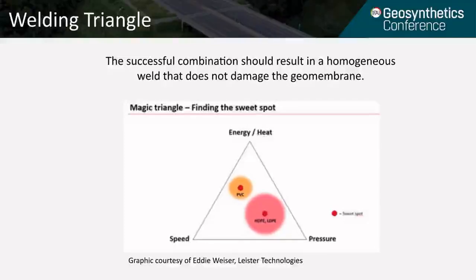As you can see in the diagram, heat, speed, and pressure can be illustrated using a triangle for each of the three components. If you look within the triangle, it shows clearly that the heat, speed, and pressure for PVC, as illustrated by the gold circle, is different than the heat, speed, and pressure required for welding the polyethylene materials HDPE and LLDPE. If you look further within the circle, there's always going to be a sweet spot where you have a better setting that's going to give you your best quality welds.